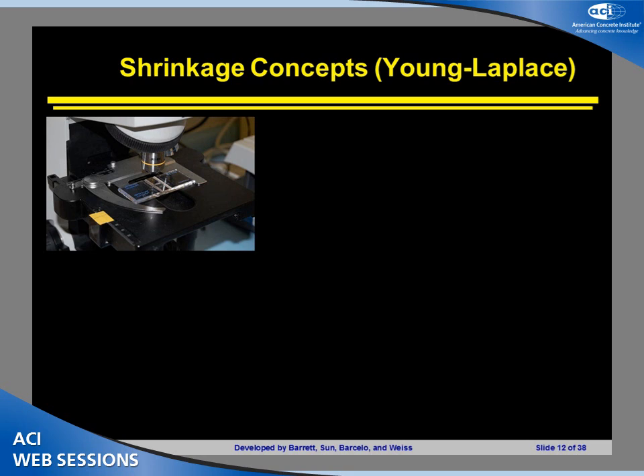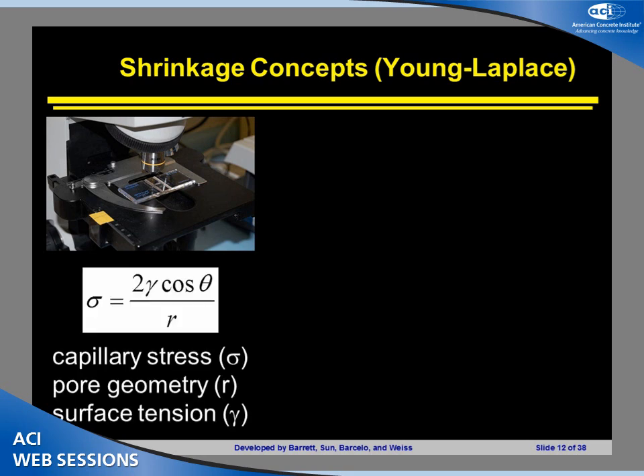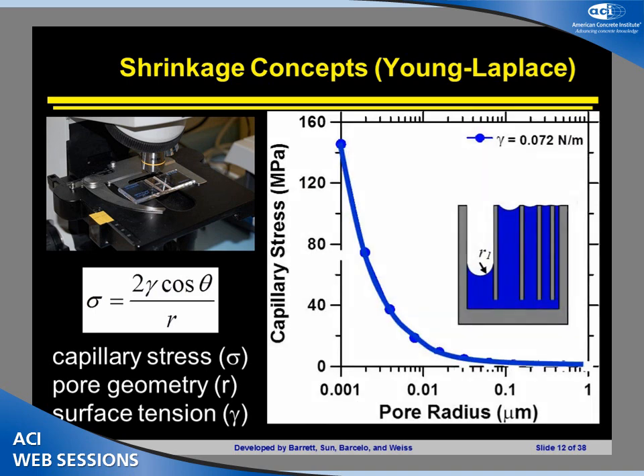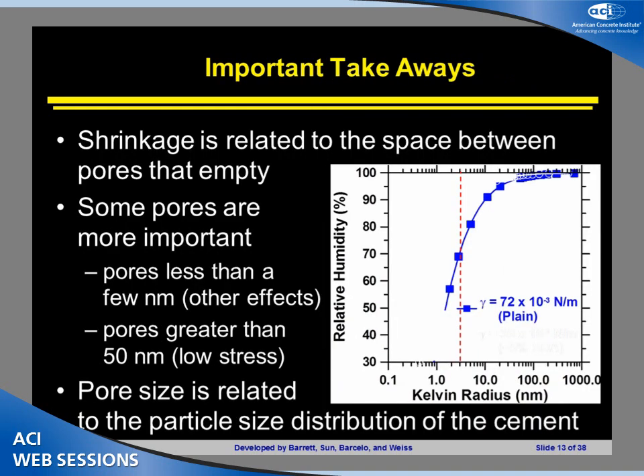High surface tension holds those 2 layers together. That's the same thing we have going on inside of the pores, inside of our system, and this is really what is going to drive the shrinkage. Again, same equation that we looked at before. The stress is related to the surface tension divided by the pore sizes inside the material, and we will keep coming back to some general plots, but here you can see the idea. The stresses are relatively low with big pores, and the stresses get much, much higher as you get to smaller pore sizes.